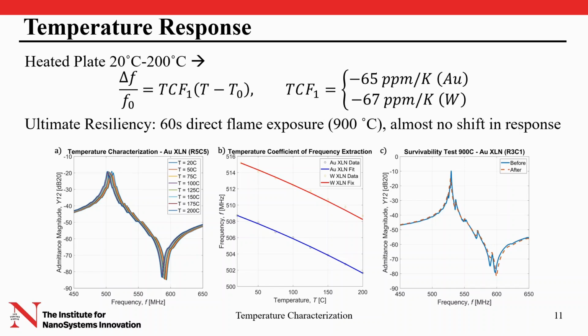These two values are very similar because the configuration of the device is the same. However, since this value is modal and there is a slight difference between the tungsten and the gold, we see the slight difference. Finally, as we're targeting harsh environments, we exposed the chip to a direct butane flame for 60 seconds at around 900 degrees C. And as we can see in the plot on the right, we have basically no degradation in the response of the gold device.